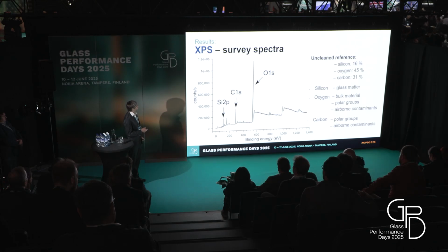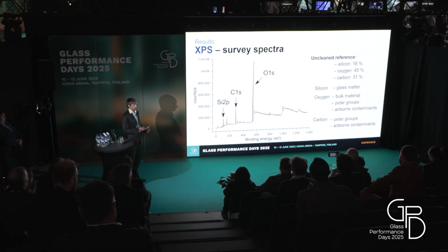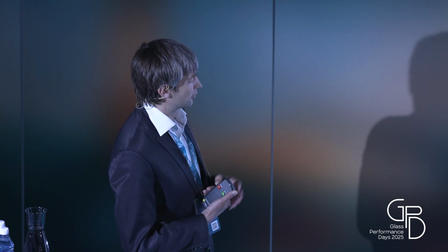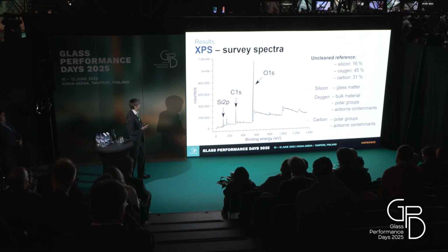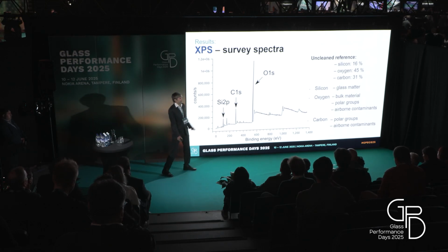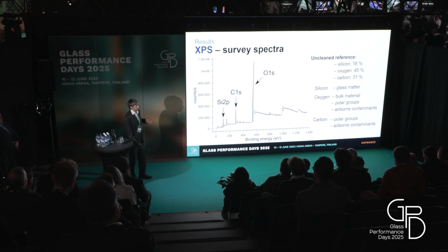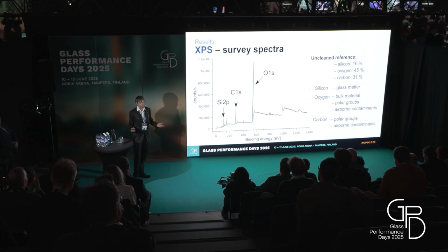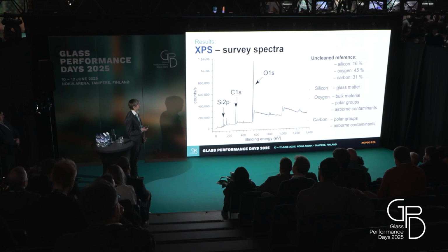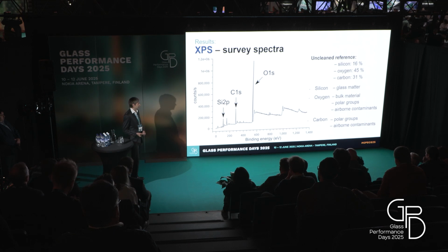And what is it then, if we didn't change the roughness? So what is behind the chemical change? So we did the XPS analysis, and this is the surface spectrum of the reference sample, which contains a high peak of carbon and also a high peak of oxygen, which is naturally in every glass, because you have some oxygen in the silicon oxide structure. And the oxygen also can come from airborne contaminants and from the polar groups we are introducing on the surface.